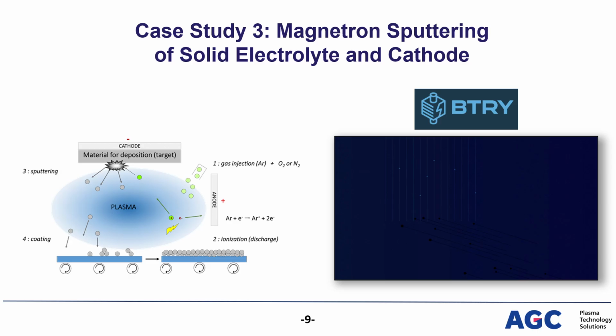The third partnership is a collaboration with the Swiss startup BTRY for the deposition of a solid electrolyte and cathode material by magnetron sputtering. Magnetron sputtering is a PVD technology where the vacuum chamber is pumped to a base pressure of 10⁻⁶ millibar by a combination of a mechanical pump and turbomolecular pumps. There can also be a need for cryogenic pumps that are very effective to catch the residual water in the